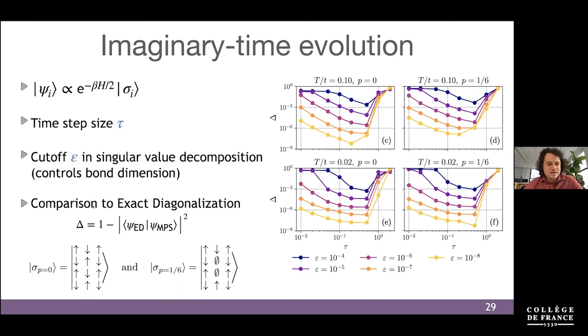And so what we did is to compare the states we developed by time evolution to exact diagonalization. If you want to compare to exact diagonalization, of course, we have to stay on smaller lattices. So here I computed the time evolution of two different states, first at half filling and then with two holes, on a 12-site lattice. Those are the states shown here. And what is shown on the right-hand side is actually the accuracy, how accurate we can get those time evolutions.